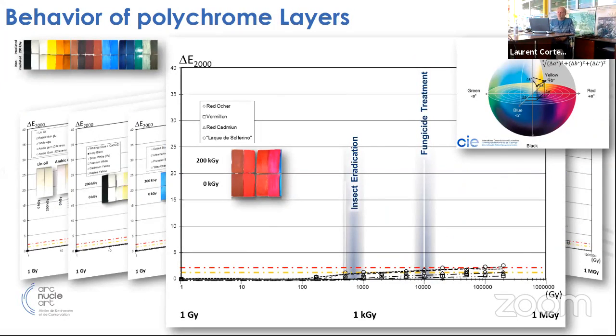Here is, for instance, some results about pigment and painting, because color change in transparent material has been the first concern. We verified that European traditional pigments and binders were very resistant to irradiation, at least until 100 kilogray, which is much more than what can be used for those treatments.